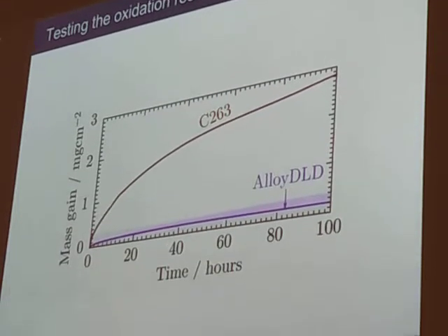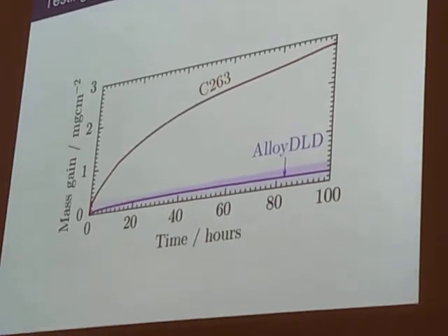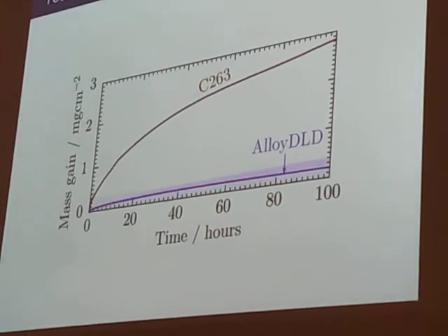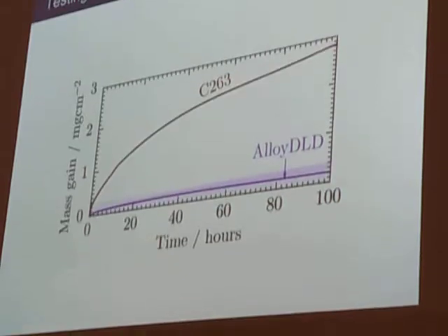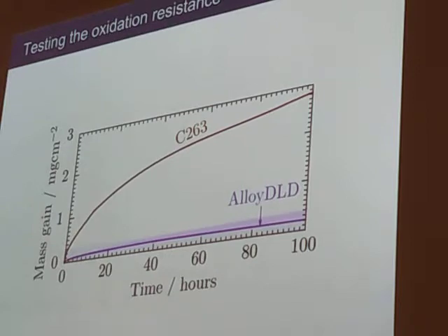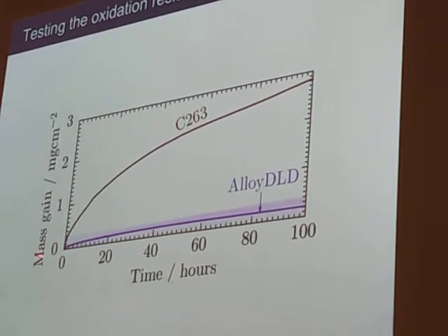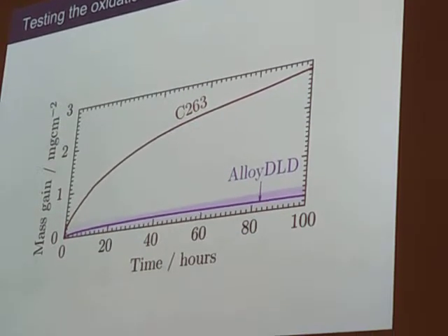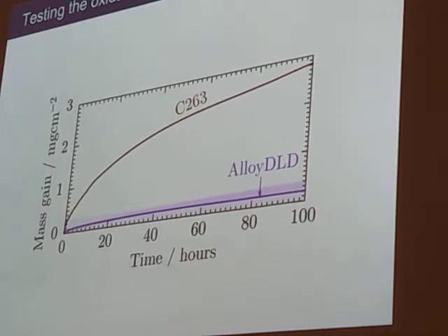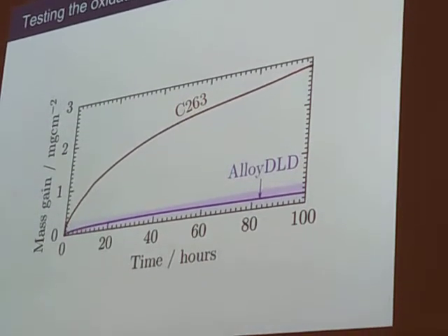And that's because we had to allow so much leeway on that processability parameter, because it was so difficult for us to predict at very large uncertainties, that we were really pushing the boundaries in almost all the other physical properties. So it's only just about predicted to work. But luckily, in this case, our actual experimental measurement, which is this darker purple line, worked a little bit better than we expected. It is within the expected threshold, and so this alloy did satisfy the oxidation requirements. So that was a real big win for us.